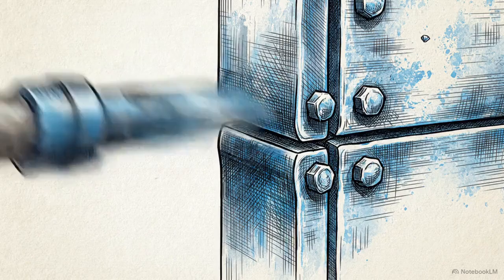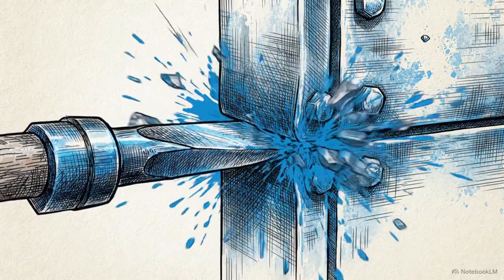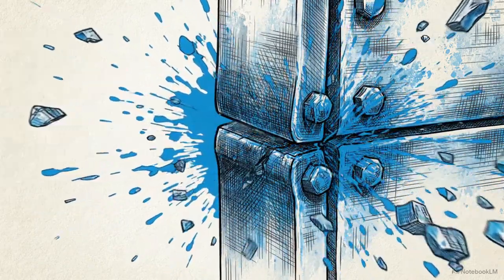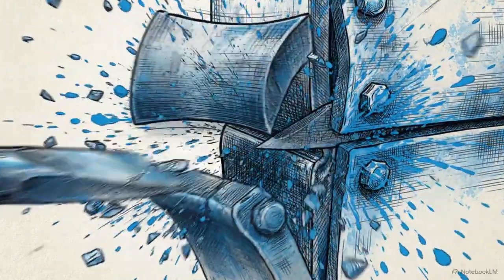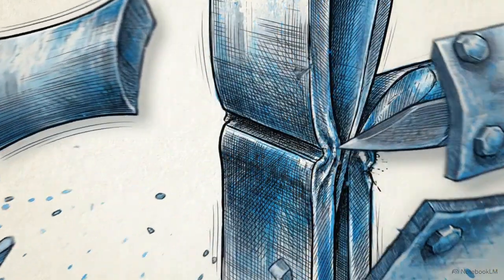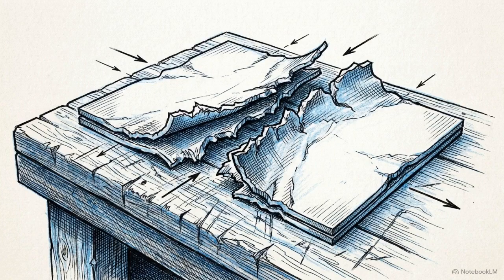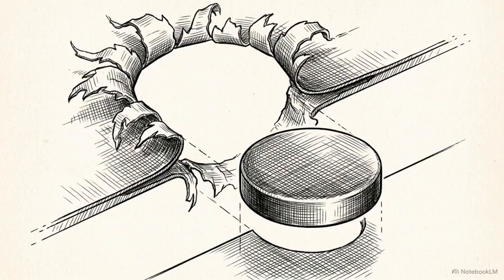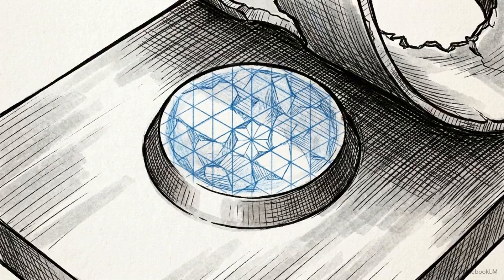Real validation demands destructive mechanical intervention. This means regularly halting the line to perform a physical peel test or chisel test on a sample run. In a successful test, the joint does not break. The base metal sheets must physically tear around the weld, pulling a solid, intact button of fused metal completely out of the opposing sheet. That torn button is the physical proof. It confirms that the molten pool crystallized into a structure stronger than the surrounding steel.